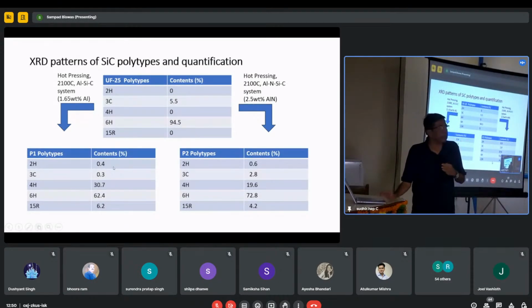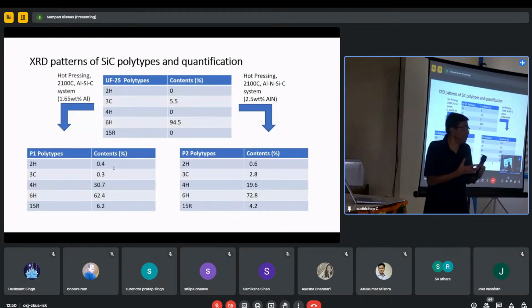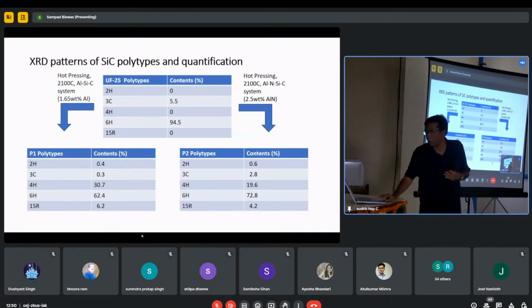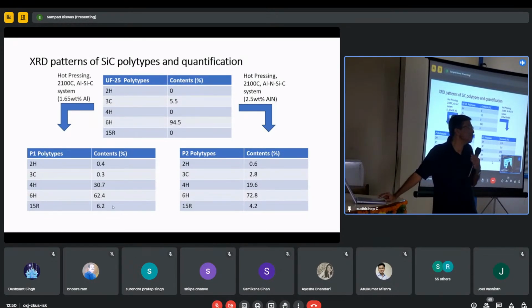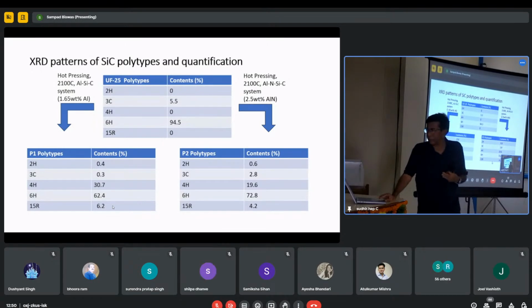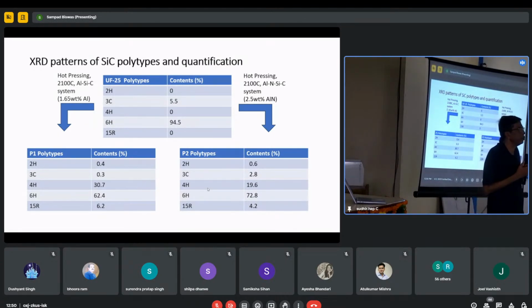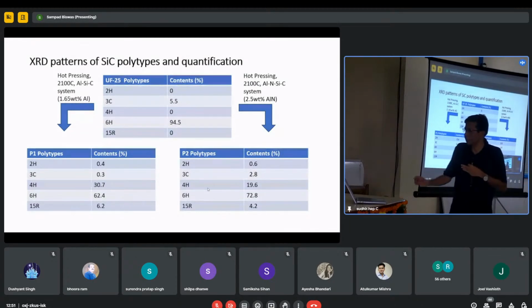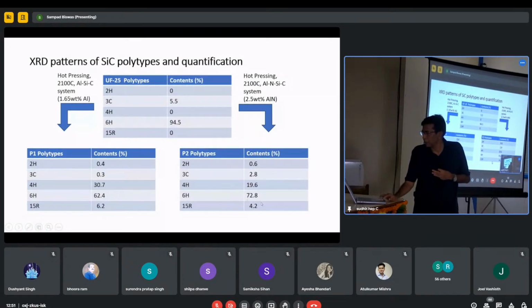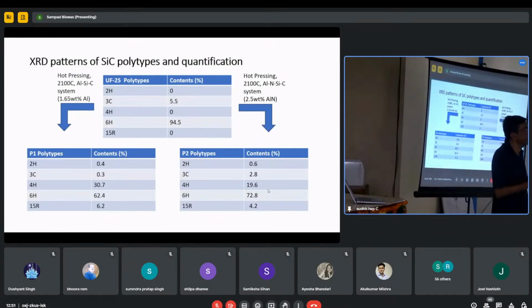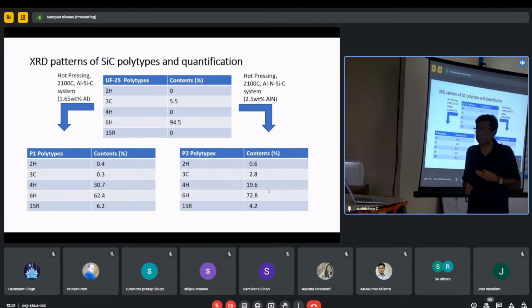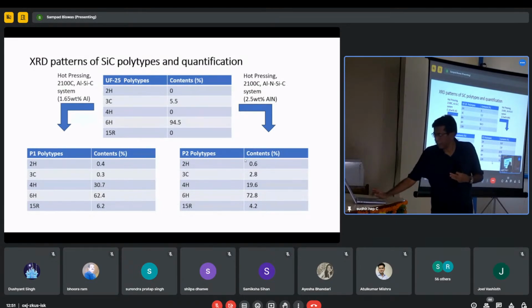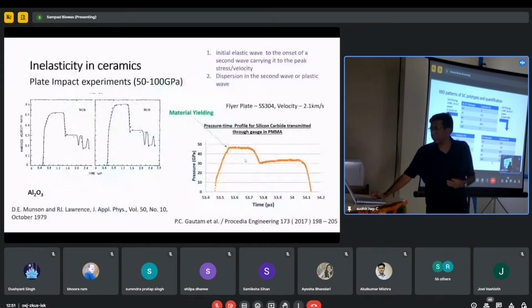Now, when we prepared the ceramics after sintering or hot pressing, what we have found is that the quantity of 6H is reduced while the quantity of 4H has increased. This is possible due to a polytypic transformation from the 6H structure to the 4H. And in some cases where you add a different additive, you find that the polytype ratios are changed. In the P2 samples, mostly the 6H variety is maintained and very few transformations to the 4H and 3C occur. This is the original ceramics I am talking about. Then I will show you how it happens after the impact with the bullet.